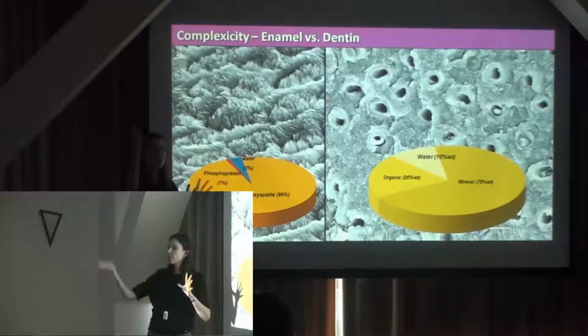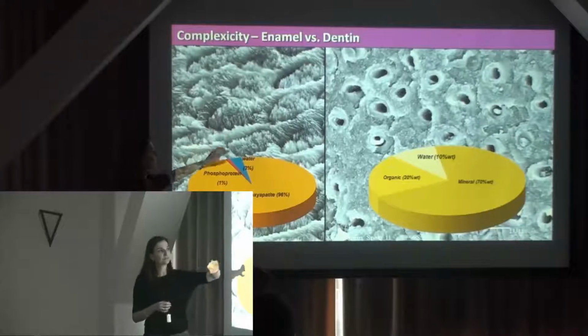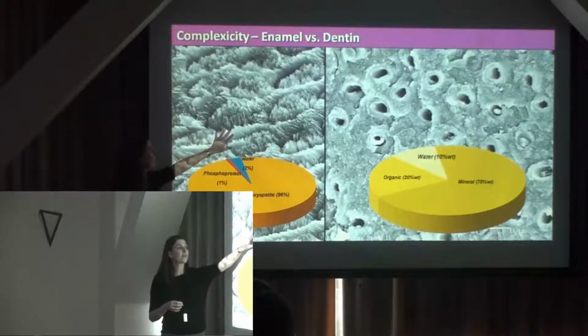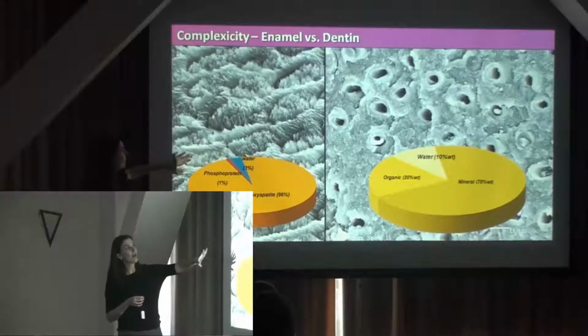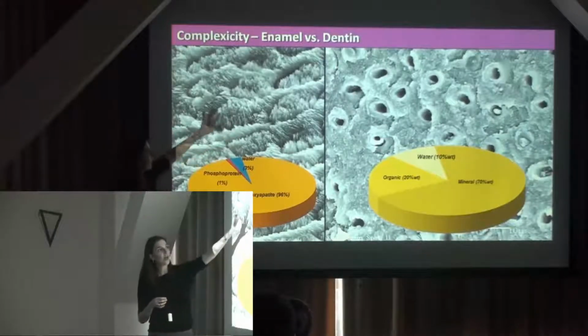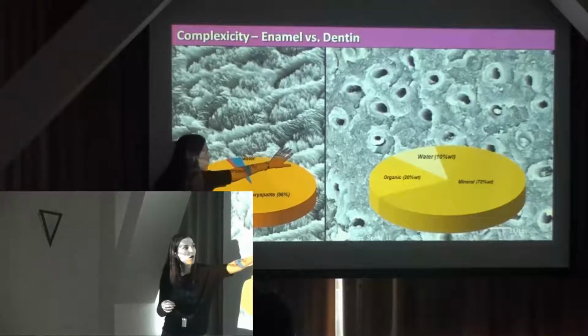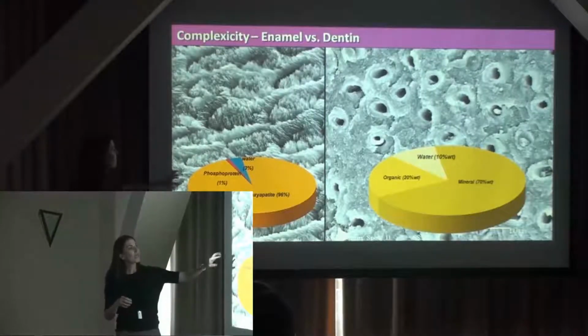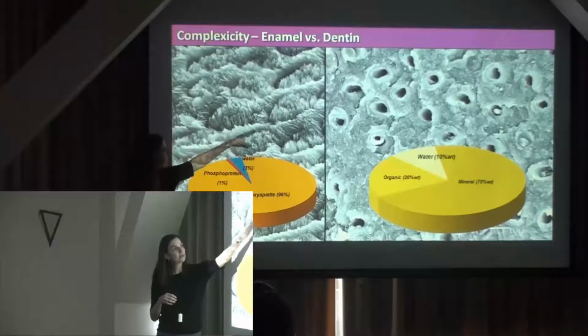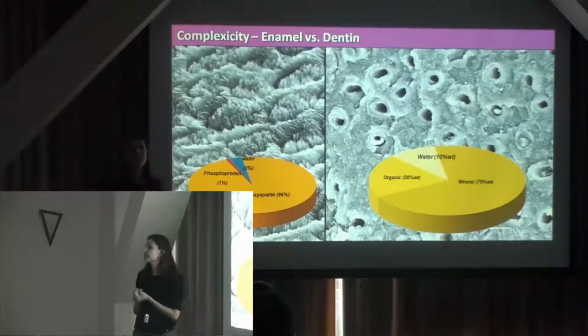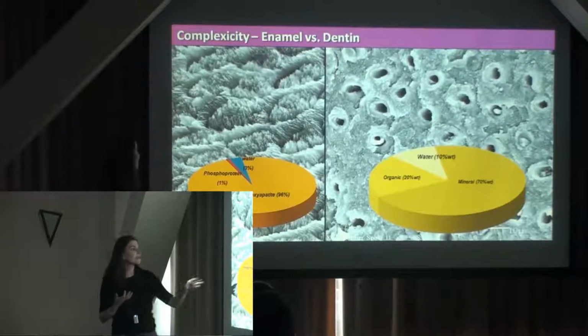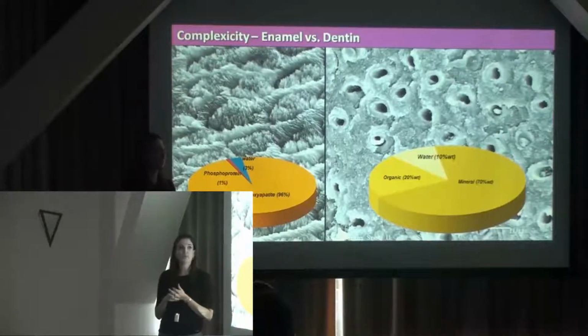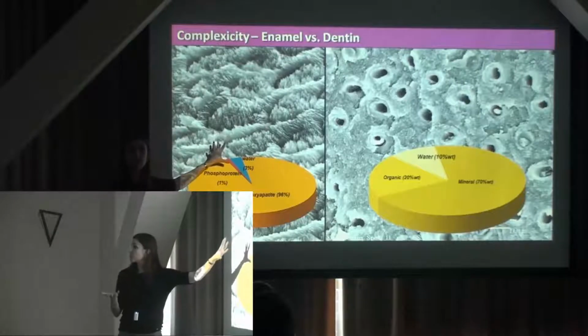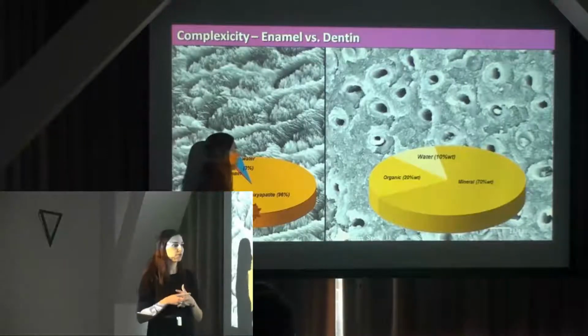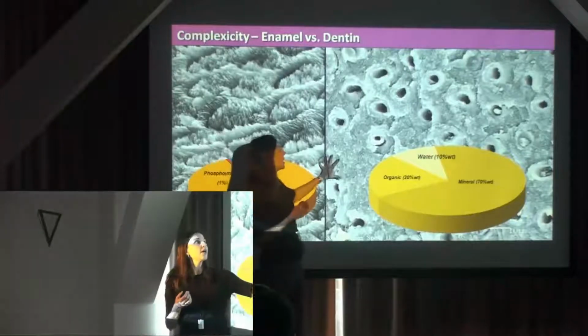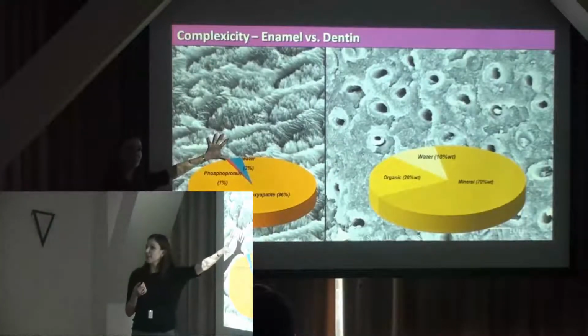What we have is a cap around the tooth that we call enamel. This is 96, 97% hydroxyapatite. You have these beautiful prisms. This is an etched surface in which you can appreciate all the small hydroxyapatite crystals. Surrounding these apatite crystals in the enamel rods, we have some phosphoproteins that were left there during the mineralization process, and about 3% water. We need this shell so it doesn't wear. That's how teeth can last such a long time in the mouth. But if our tooth was all made up of this, it would crack.